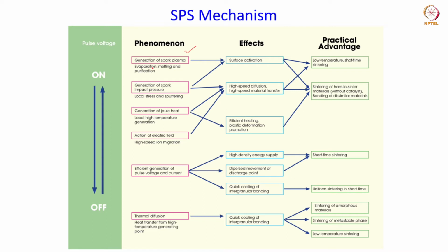And then due to this sparking between the particles, intense heat is generated, and due to that there is evaporation, melting and purification. Okay, so due to the intense heat, the particles also melt at the contact points, and evaporation also takes place, and that in turn leads to the purification of the surface of the particles. Okay, so that's about the surface activation. And the practical advantage that you get out of this is the low temperature and short time of sintering, because the densification process is all about bonding between the particles, and when you have a clean surface, that bonding becomes easier, and therefore the sintering can be done at a lower temperature and the sintering time also can be lowered.